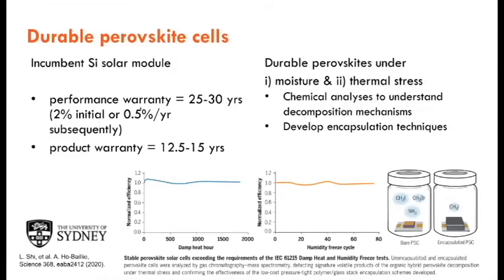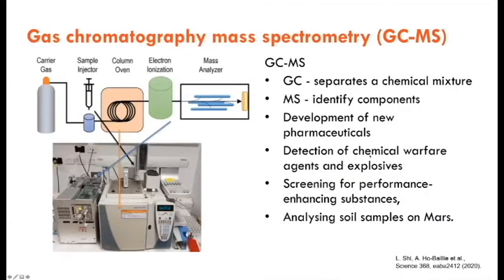So what we did is we try to understand what happens when they are being stressed thermally, what are the pathways to decomposition. And if we understand how they decompose and what can stop them from decomposing, we can develop stabilizing strategies, and in this case, encapsulation. And I will explain why encapsulation actually helps the thermal stability. So first of all, we used this technique called gas chromatography mass spectrometry to look at the decomposition products. So it's not a new technique.